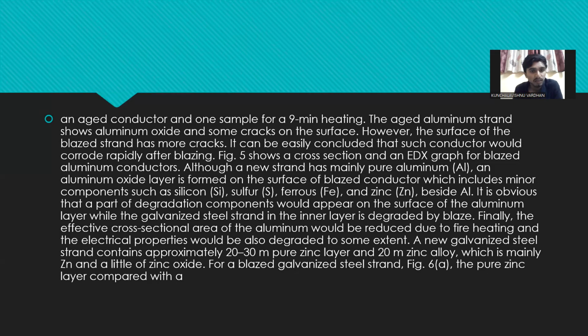It is obvious that a part of degradation components would appear on the surface of the aluminum layer while the galvanized steel strands in the inner layer are degraded by the flame. Finally, the effective cross-sectional area of the aluminum would be reduced due to fire heating and the electrical properties would be also degraded to some extent.